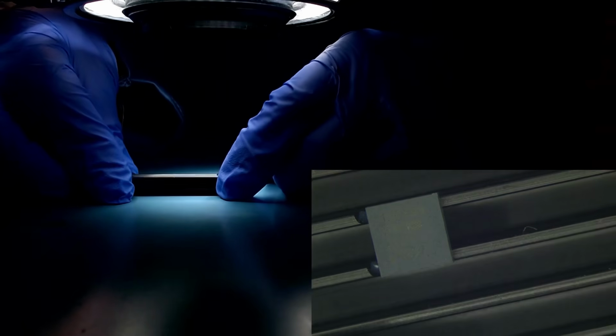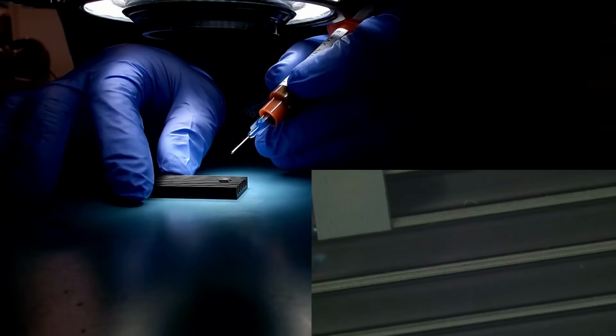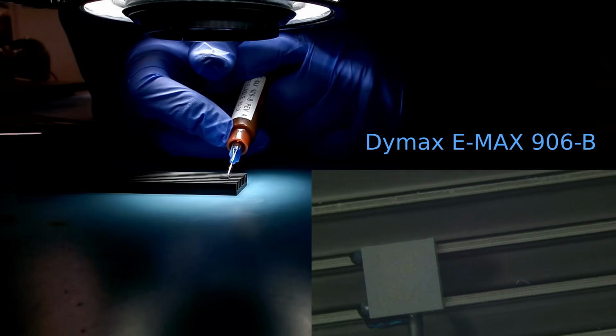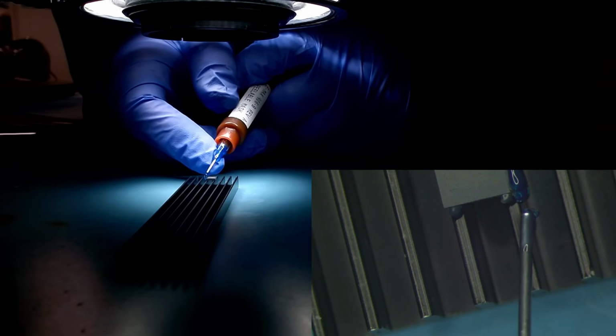So now the next step is going to be to cover the sides and the pins with our removable masking material so that we don't have any acid damage to parts of the package that we're trying to keep. I do know that the size of the die is about 2 millimeters on a side roughly, and the package is around 4 square, so we want about a 1 millimeter boundary around there. But before we do that, we're going to have to start building up the mask on the side of the package. Just going to start building up some of this masking material on the side, and then we're going to continue on here.